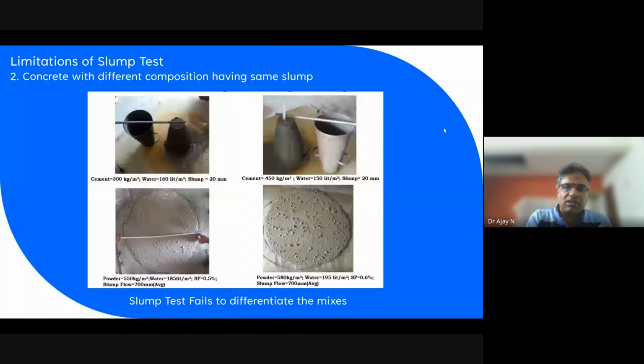Which mix is better? From a strength point of view, yes, 450 is maximum. But I cannot accept it, because although the strength point of view is acceptable, from the economical point of view it is not, because with almost 450 we can get shrinkage cracks. So I cannot accept it. But the point here was that we cannot differentiate the mixes.